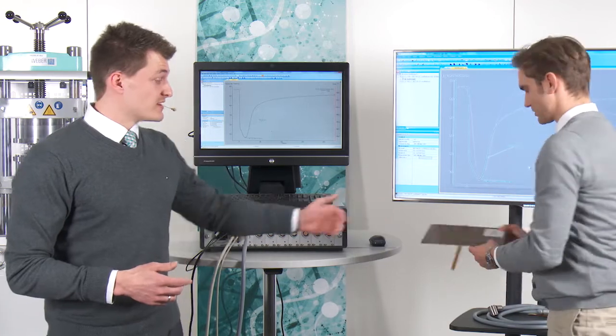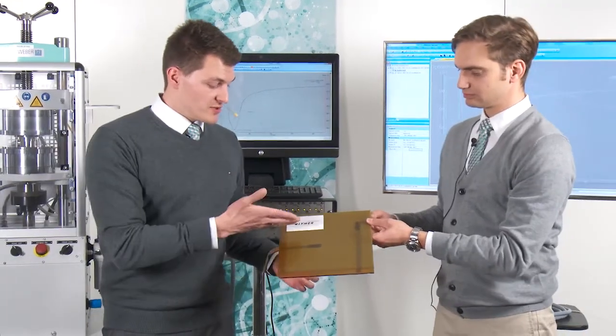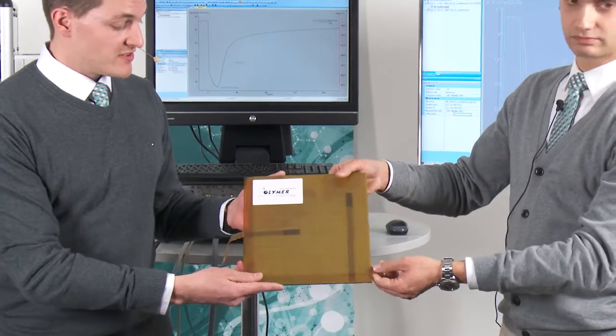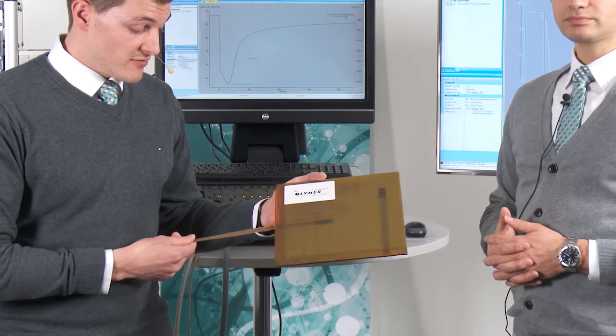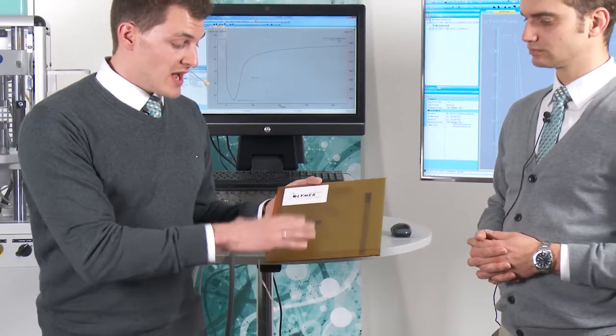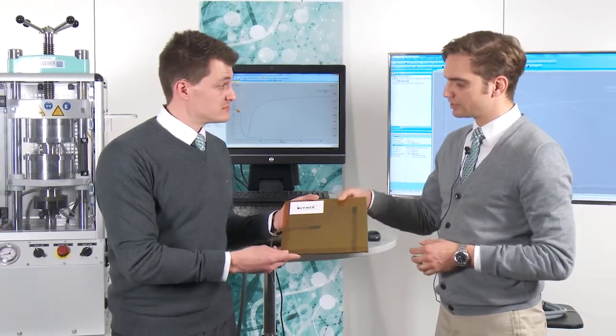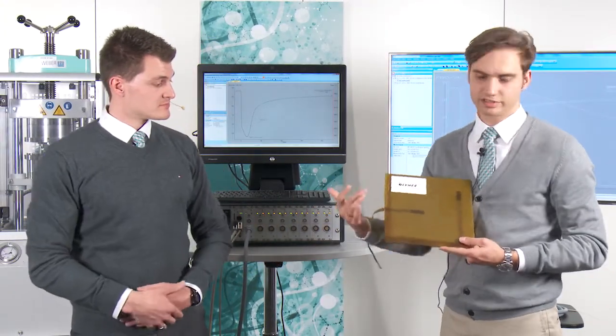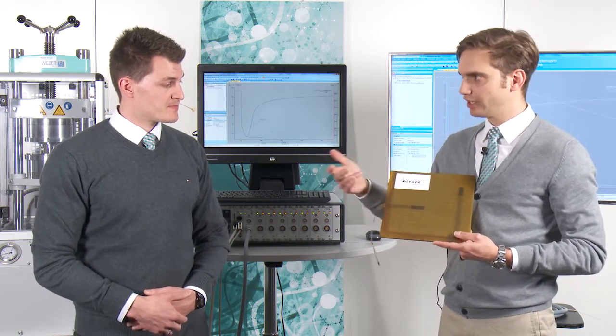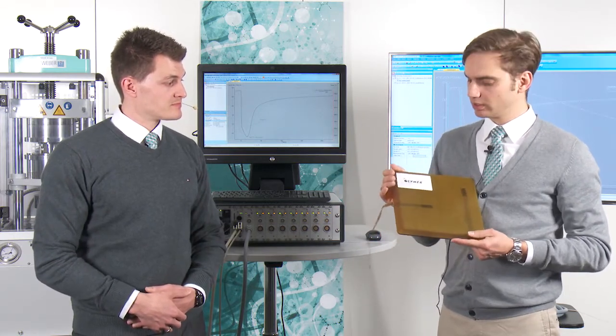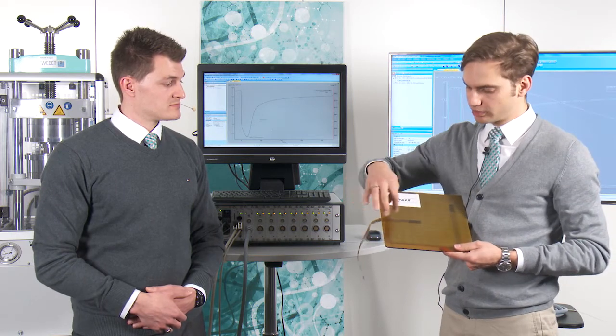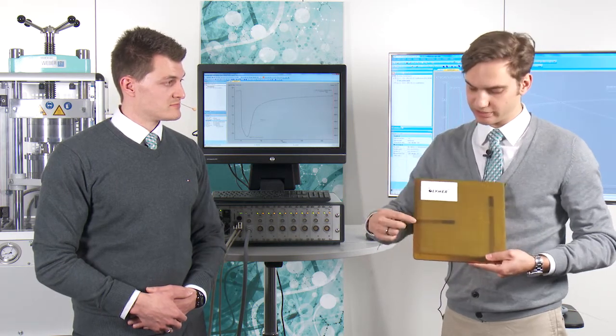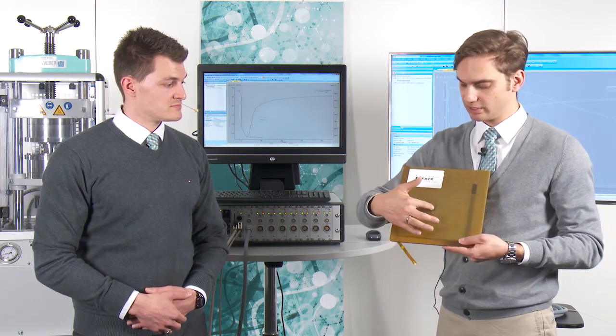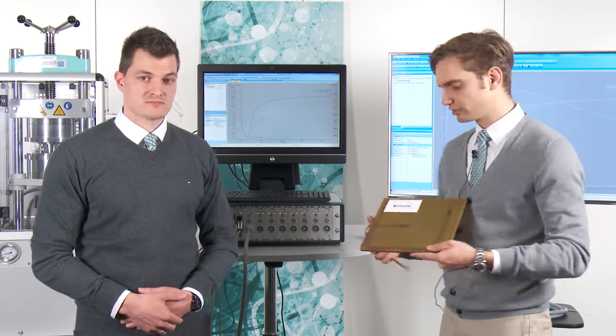We have an example here for an RTM process. This was done with the polymer engineering of the University of Bayreuth. We used an IDEX sensor inside the mold here that comes off to the DEA 288, and we monitored the flow front and the curing behavior of this material. In this case, this is a demonstrator from the lab tool they had at the chair of polymer engineering in Bayreuth. We used this glass fiber layup to see the sensor. So you could see in between, this is dielectric IDEX sensors that we could also use.